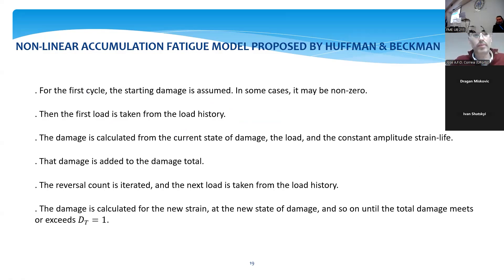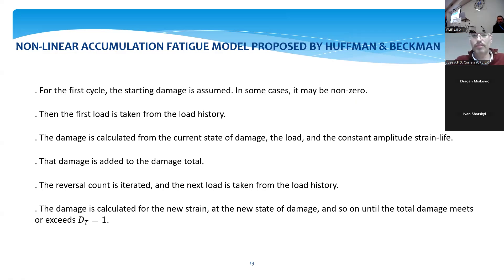How we implement the non-linear accumulation fatigue model proposed by Huffman and Beckmann: for the first cycle, the starting damage is assumed; then the first load is taken from the load history; the damage is calculated from the current state; that damage is added to the total damage; the reversal count is iterated and the next loading is taken from the history; then the damage is calculated from the new strain, or stress, or energy at the new state of damage — and so on until the total damage meets or exceeds one unit.